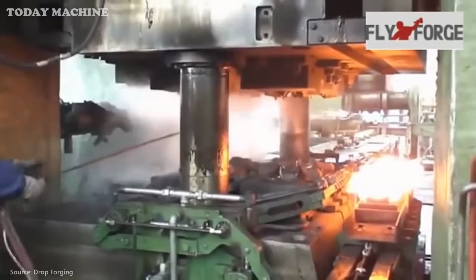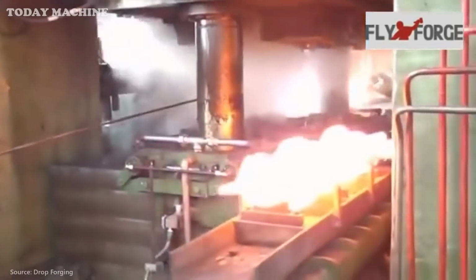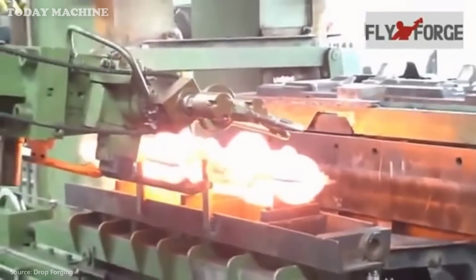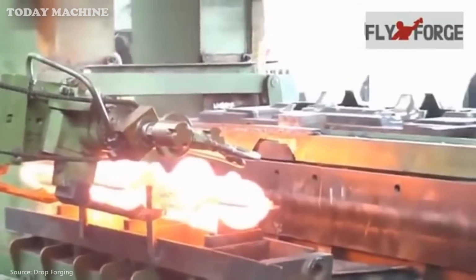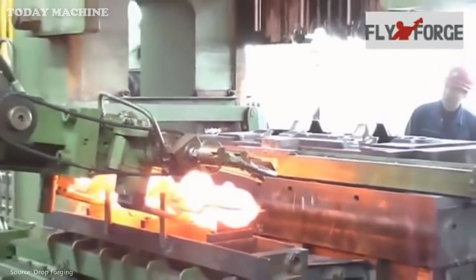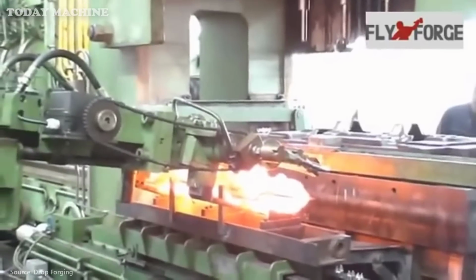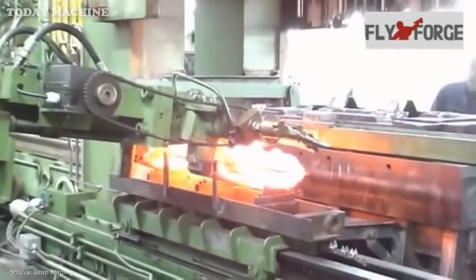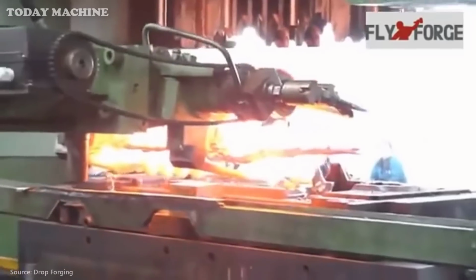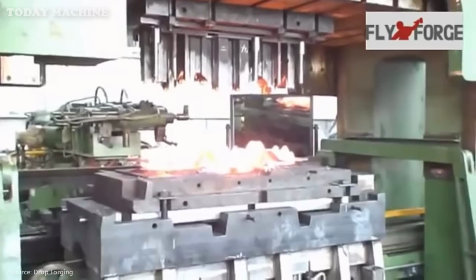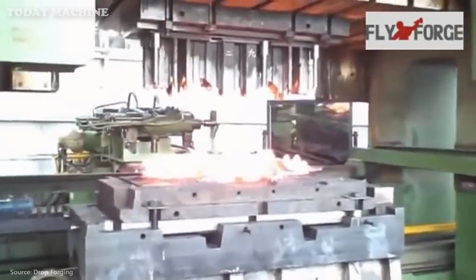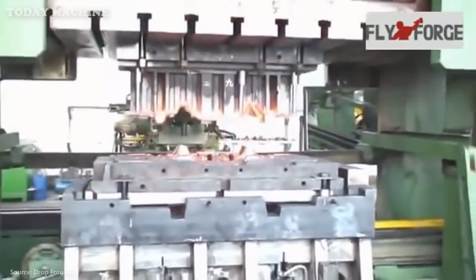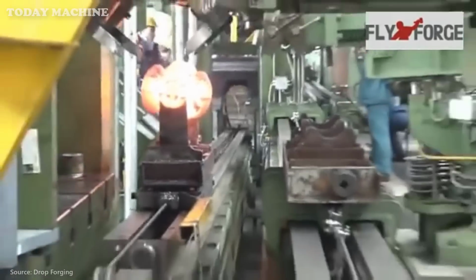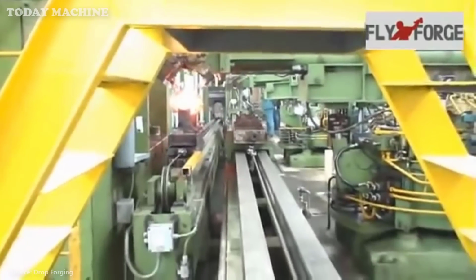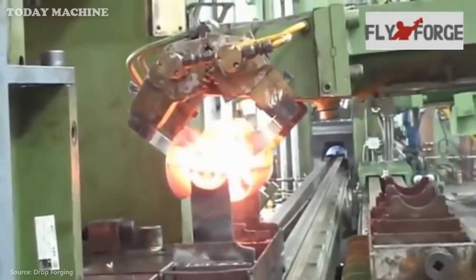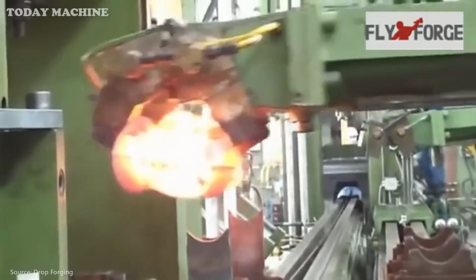The crankshaft undergoes twisting on specialized equipment at 950 degrees Celsius to 1050 degrees Celsius. Twisting ensures correct alignment and geometry by applying calculated torsion forces. Calibration is conducted twice using a hydraulic calibration machine. The first correction ensures straightness of the main shaft and proper angular alignment between rod and crankshaft diameters.